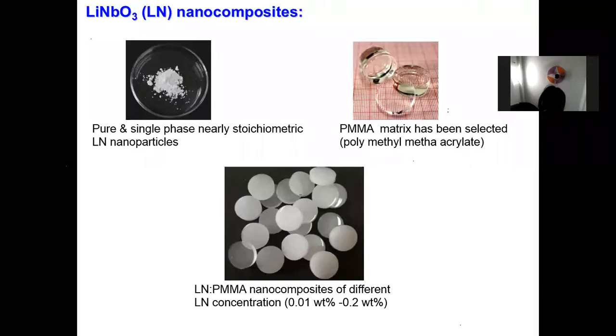And then we take the PMMA matrix, which is polymethyl methacrylate, which is generally used for making this composite. These nanoparticles are put in this PMMA matrix, and you can have these discs of nanocomposites, and that can be used in place of a single crystal, because single crystal lithium niobate is very difficult to make. It takes a lot of time. It is very expensive also.